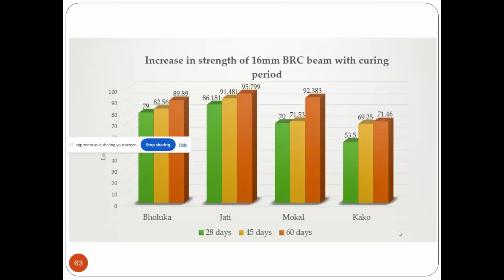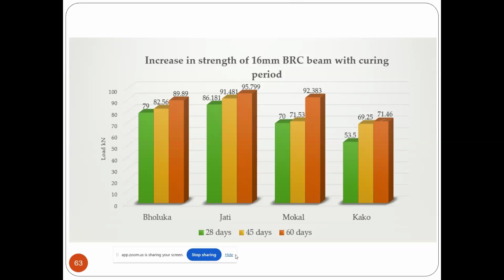The results were just like that. The beams were tested for 28 days, 45 days and 60 days. This is normally in the flexural testing machine. The maximum load they carried was, for Bholuka Bah, 89.89. For Jati Bah, it is 95.79. For Mokal Bah, it is 92.383. And for Kako Bah, it was 71.46. This is in the flexural testing machine.